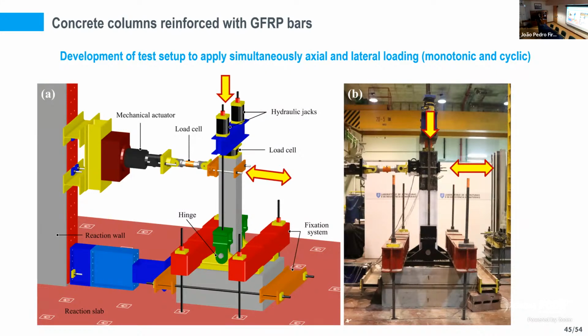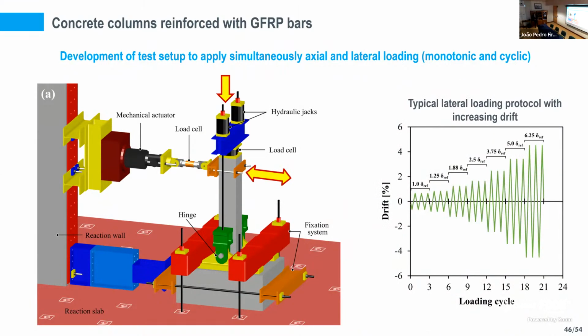And for that, we developed experimental tests here at CERIS laboratories. The columns and the footing were pre-stressed against the strong floor of the laboratory. We designed a test setup that was able to maintain a constant load on the concrete column while lateral displacement was applied to the columns, either monotonic or cyclic. And for the cyclic loading, we adopted the typical loading protocol with increasing amplitudes of lateral displacements.